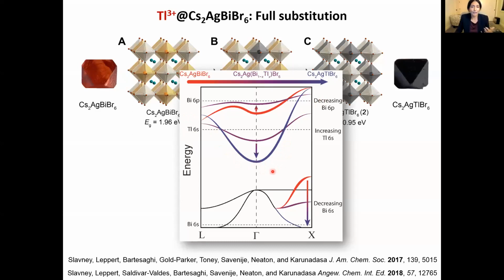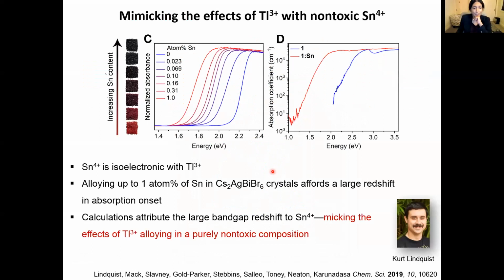So we can then ask what other ions have empty 6s orbitals. And we don't have to look too far to come up with tin 4+, which is isoelectronic with thallium 3+. We know tin 4+ goes into a double perovskite. And this just works like a charm. Alloying tin 4+ into the silver bismuth double perovskite basically mimics everything we saw with the thallium 3+, but now in a purely non-toxic composition.